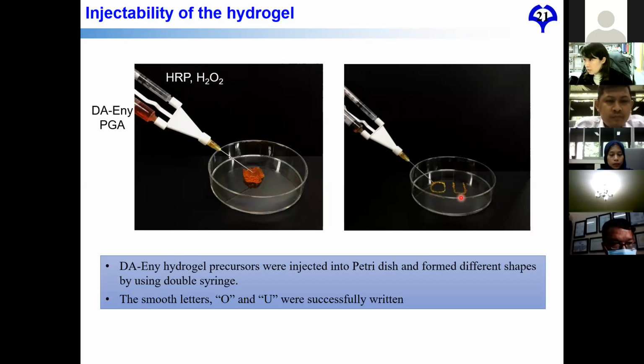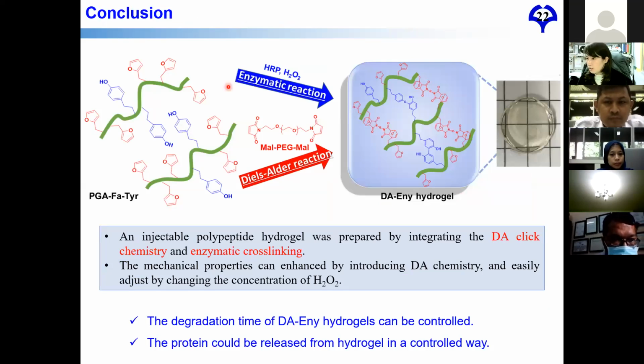So using these two kinds of cross-linker, first, because the enzymatic reaction is very fast, we can quickly form the hydrogel by the enzyme. And then because the other reaction will take time, after injection the hydrogel can become stronger after maybe 1 hour to 2 hours.